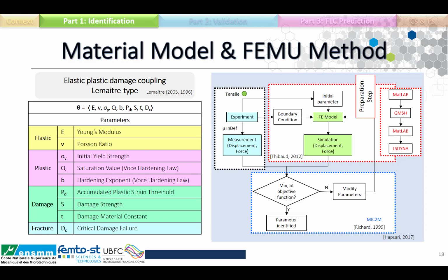As you can see in the flowchart in the right part of the screen, there are three parts to this identification. One is the experimental test, in blue here. One is the numerical simulation, here in red. And the last one is a minimization step using a homemade toolbox based on the Levenberg-Marquardt algorithm. So we use a finite element model updating method in order to obtain the material parameters from the micro-INDEF test.